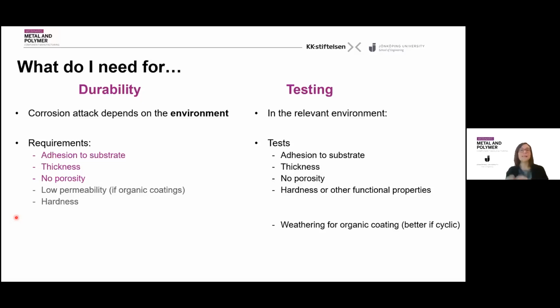You cannot test the coating alone, because the system is an integrated system, and the final properties are given by the combination of the substrate, cleaning, pretreatment, coating, and the process you chose to apply the coating itself.